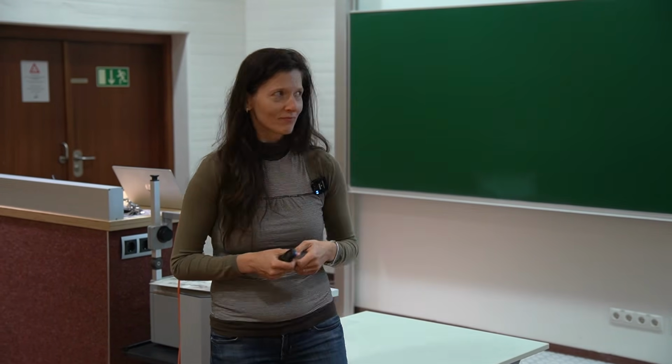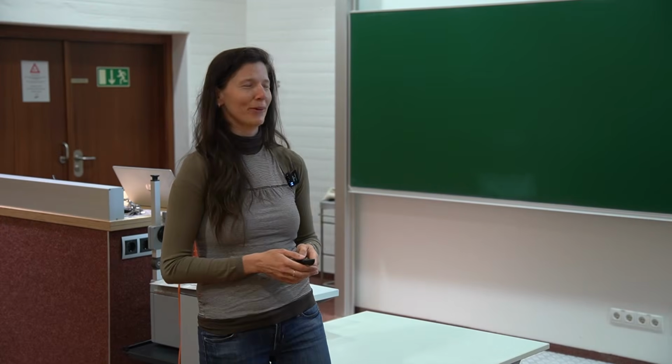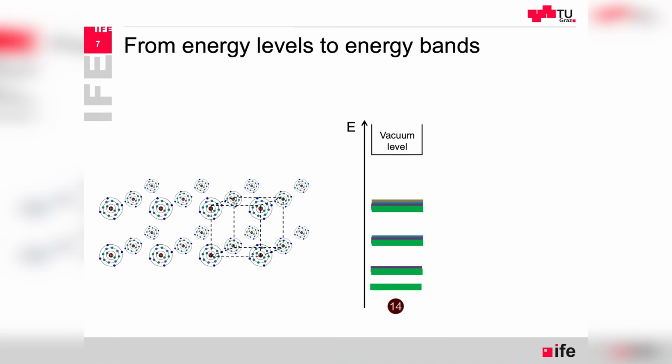So this analogy will not work when we talk about 10 cyclists. Then we have to forget about this simplification, but with atoms it still does work. If we have a system with multiple atoms, and that's what we have in crystals, in the semiconductor, then each atom alone has the same set of energy levels, but when we consider them all together, we have to have the shift, the split in the energy levels so that we can accommodate all of the electrons in the system. So this creates these energy bands.